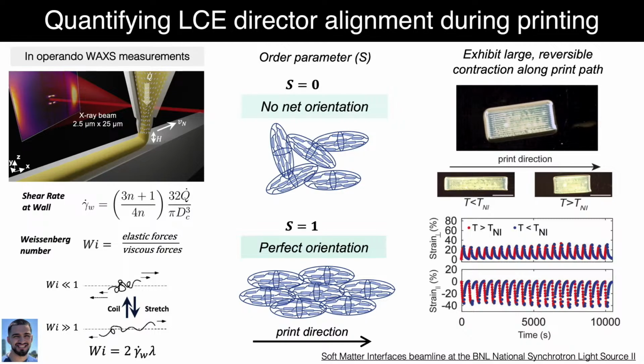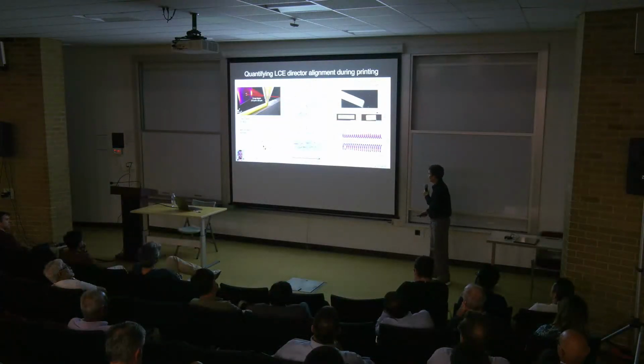At the beamline, we could do in operando measurements. As we're actually printing, we have a 3D printer set up at the beamline. We helped work with them to create a printer that would be useful for what we're doing. We're carrying out wide-angle X-ray scattering measurements. We have a beam size that's actually quite small, 2.5 by 25 microns. So we're able to go up and down the nozzle vertically and look at the alignment that's encoded, but also radially across the nozzle. At the wall, you have the highest shear stresses. This is where we'd expect to see the greatest director alignment. And of course, at the nozzle exit is also where we would expect to see the highest alignment.